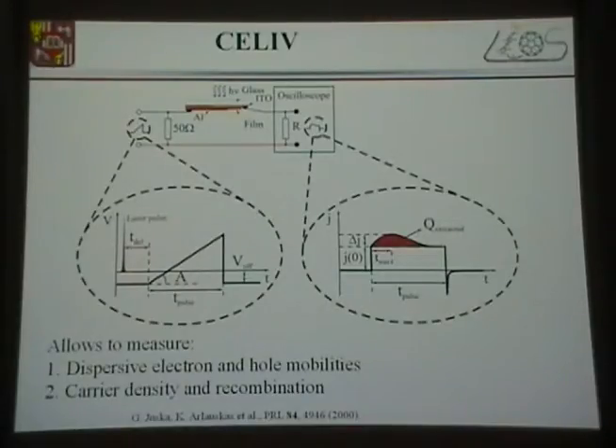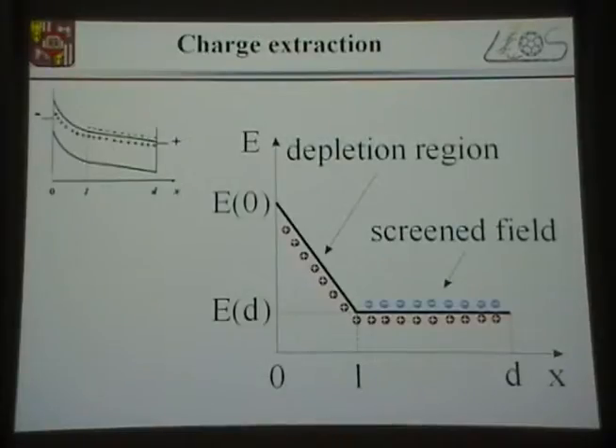And you see, you measure the response, and from this response you get all the information. But the main idea is that if you have a film, and you have charge carriers in the film, say, generated thermally in equilibrium, then by applying the voltage ramp, you start extracting the charge carriers towards the electrode, but you don't inject the new ones. All right, so this is exactly the process you see in this picture.